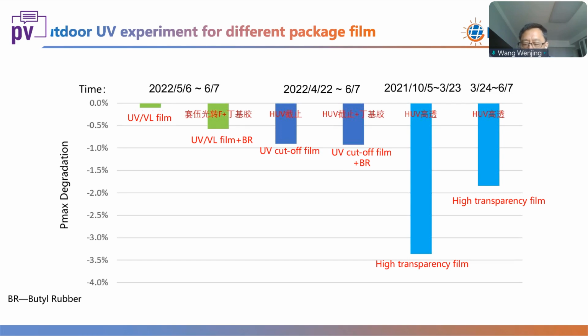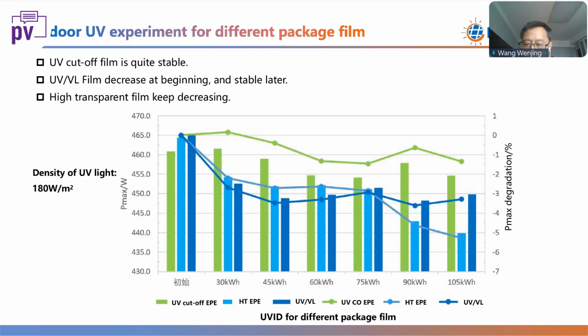For these different kinds of package film, there's an outdoor experiment. We can see the UV to visual film is quite good, and the UV cutoff is also good. But for the high transparency film, the power degradation is very serious.